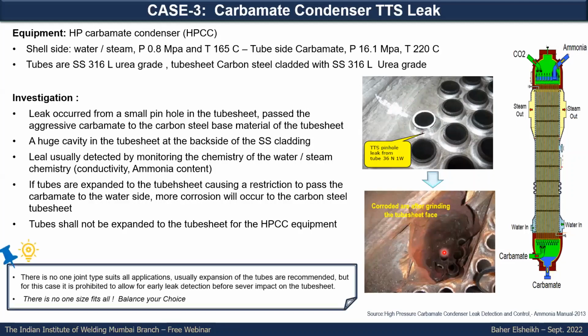That's why, as we said, there is no one solution that fits all. In the previous case history, we said crevice corrosion shall be closed by proper expansion. It is highly crucial, and you have to follow this. But in this case, it is highly recommended not to do expansion and to leave a clearance or gap between the tube and the tube sheet hole, so that in case of a leak like that, it will pass easily to the shell side. Once it passes to the shell side, there is online monitoring of the water parameters here, so the conductivity will increase sharply and ammonia will be detected. So you might have good time to attend to the equipment before having such a massive impact on it.